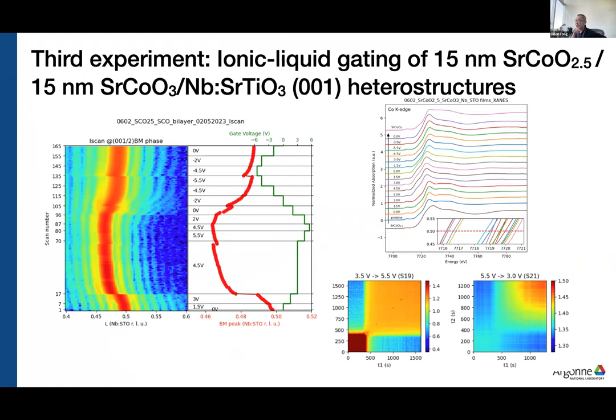This was taken at sector 8. This is a bilayer of the brownmillerite with the perovskite. These are L scans. I'm showing you a map of L scans on the left, taken at different voltages. You can see that at these different voltages, you can inject or remove oxygen vacancies. We also did measurements of the cobalt K edge, so we could see how many vacancies we're putting in or taking out. The two-time correlation maps are shown at the bottom right.